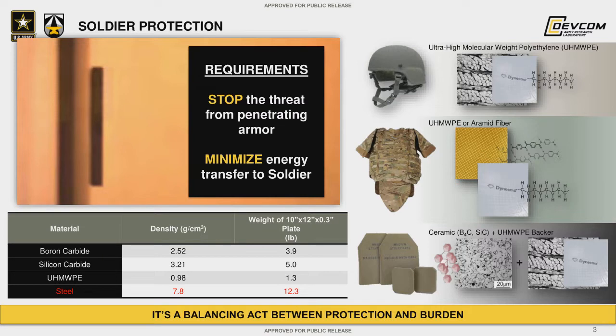Then at the bottom right, we have what is the highest level of threat protection, which is a ceramic, typically boron carbide or silicon carbide strike face on an ultra-high molecular weight polyethylene backer. The ceramic here is really the critical part for advanced threat protection because it has a very hard and very strong surface, which is really excellent at ablating away the materials or the projectile and providing a high level of protection against high energetic threats, but comes at the cost of somewhat increased density over other materials.